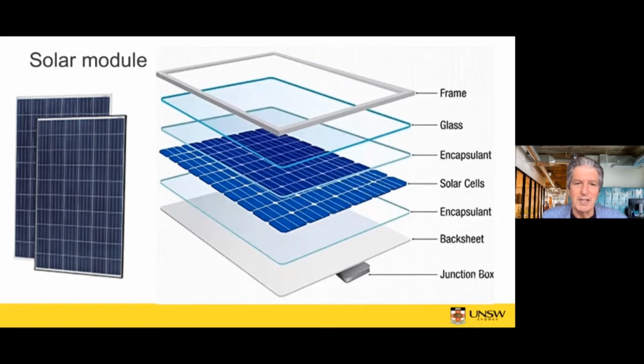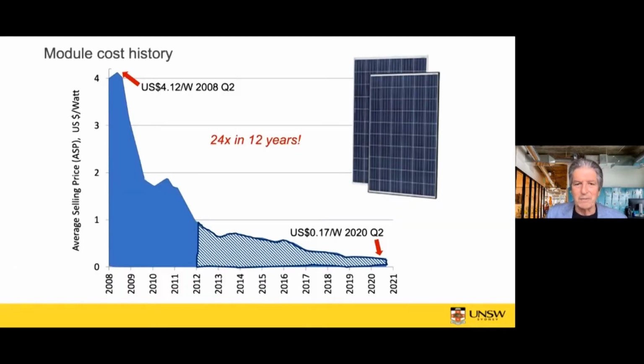So basically you have a glass cover sheet. Your glass is a very cheap, strong, transparent material, and you laminate the connection of silicon cells between that glass sheet and a polymeric back sheet in general. So you have a glass top sheet, and then you have a frame glass, and then these encapsulant layers serve both as an adhesive, bonding the whole module together, as well as a soft layer that allows for differential expansion between the cells and the glass and the back sheet and so on. So it absorbs some of the thermal stresses that you get in the module.